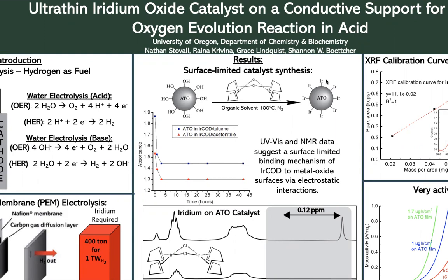UV-vis data suggests that this binding mechanism is surface limited, which can be seen as the absorbance plateaus after about 2.5 hours, showing iridium is no longer adhering to the surface of the metal oxide. This is likely because the reaction is limited by the surface hydroxyl groups of ATO.